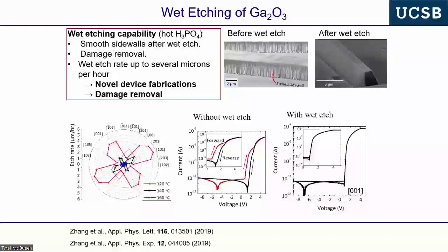crystallographic orientation, so we can look at the crystallographic dependence of the etching, and then we dry etch the structures, where we get essentially direct transfer with a hard etch mask on the structure. We get visible sidewall etch features, and then into this, there's ion damage from the etching. And if we make Schottky diodes on this, then we get lousy Schottky diodes with large hysteresis. So these are the sweeps in the Schottky diodes, from the hysteresis.